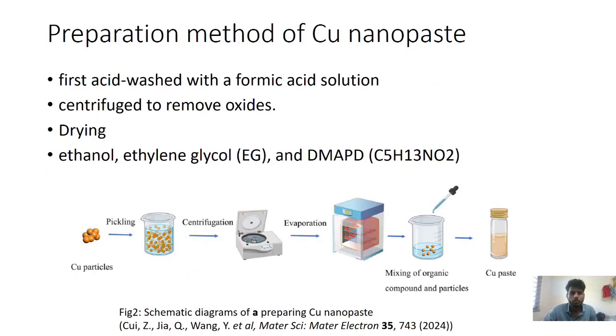So firstly we discuss the copper bond. For formation of a copper bond, we first have to make copper nanopaste, in which we take the nanoparticles, wash them in an acidic formic acid solution and centrifuge to remove the oxides present on the surface of the copper nanoparticles. Then we go to the drying process and then mix it with some organic components such as ethanol, ethylene glycol, DMAPD for making the copper paste.